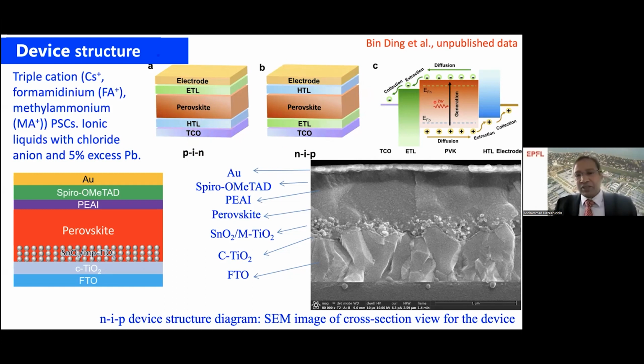So what happens in this configuration? You have an ETL layer and a hole transporting material. In both cases, the perovskite is sandwiched between the ETL and the hole transporting material. When light is shined onto these materials, you instantaneously create charges, positive and negative. The negative charges are extracted into the ETL layer because of the band alignment, and the positive charges are well aligned with the hole transporting material, so the positive charges are extracted into the hole transporting material. This way you collect all the charges at the interfaces.